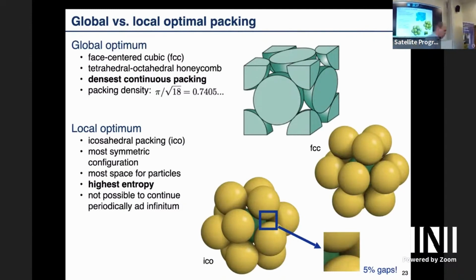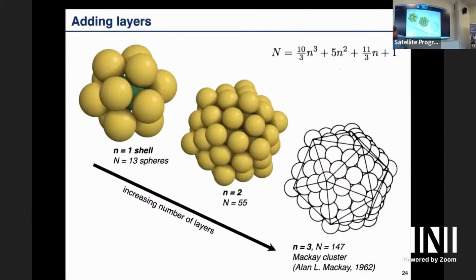And the competition of these two local orderings is what makes spheres a bit special, and what also explains why in glasses you often have icosahedral order, because if you do it quickly, you get something like this, and why in the crystal you go to densest packing, you eventually end up here. And the Frank-Kasper phases you've seen before are sort of a compromise. They are still pretty close to icosahedral order, not perfectly, but they sacrifice density to get more icosahedral order. That's also why we see them as intermediate states in our simulations.